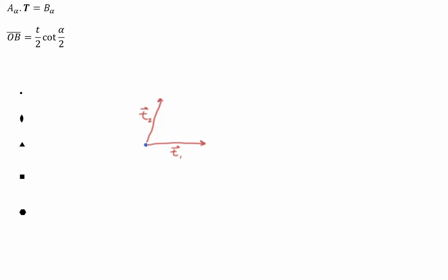And so any integral number of lattice combinations away, I will find a new lattice point. T1 plus T2 would bring me here. And I can fill up all of two-dimensional space by repeating this original lattice point indefinitely. Another way to say this is that any lattice point can be described as an integral combination of these translation vectors. So this is 2T1 plus T2. It gets us from the original lattice point to this new lattice point out here.